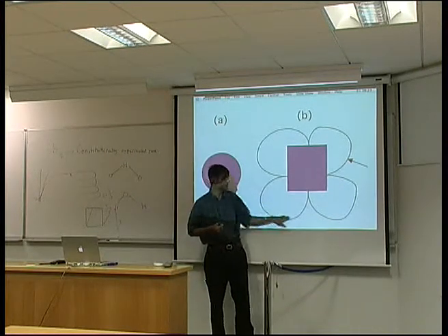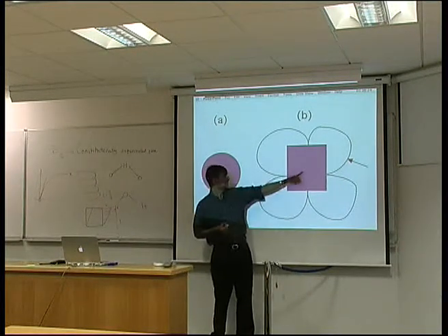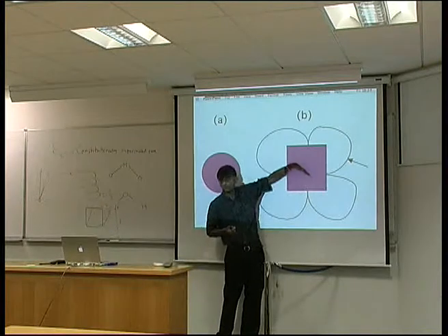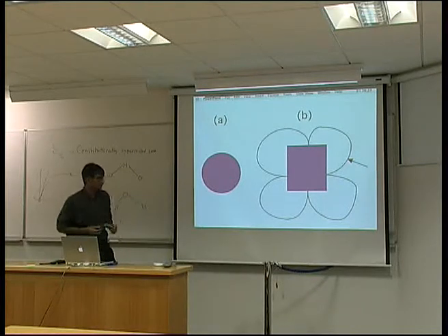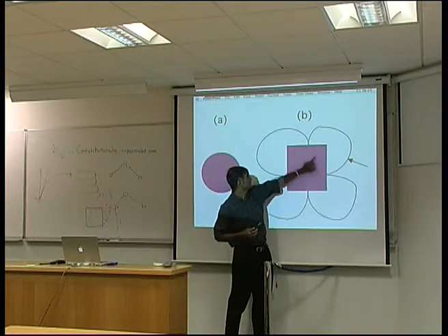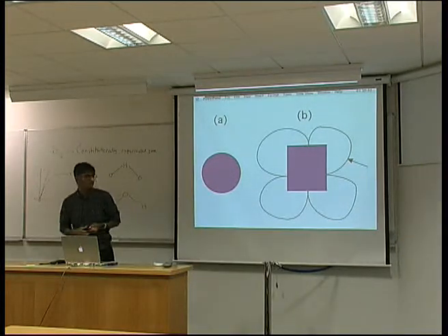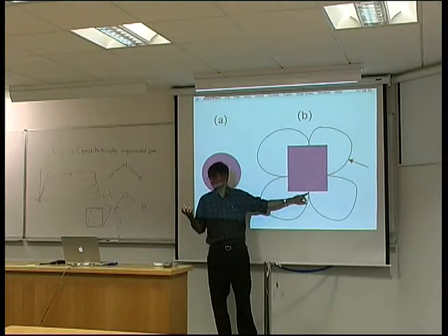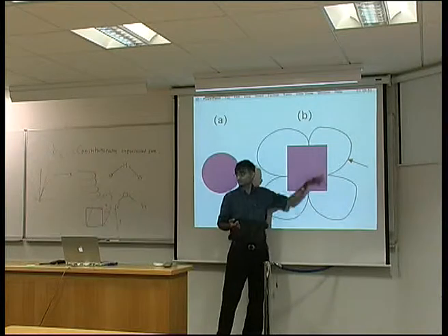Okay? So this is known as a gamma plot. It's plotting the surface energy as a function of orientation. Any vector from the origin gives me the magnitude of the surface energy, and it is normal to the plane that we are looking at. Now, in this case, obviously, that is the minimum in interface energy. That is the minimum in interface energy, and so forth. And there is a theorem known as the Wulff theorem, which says that if you construct planes which are at 90 degrees to those cusps, this is called a cusp, then that gives you the equilibrium shape of the precipitate.